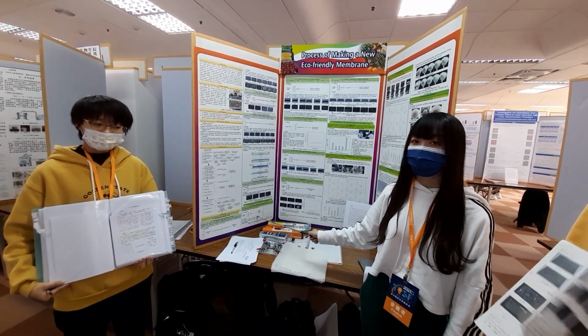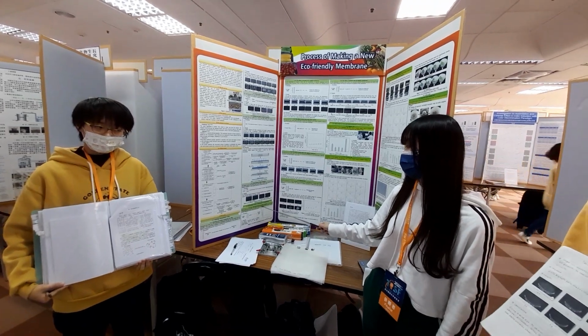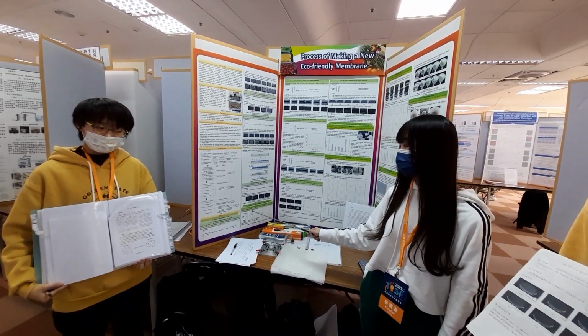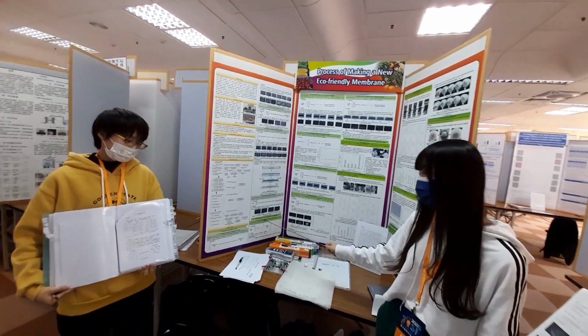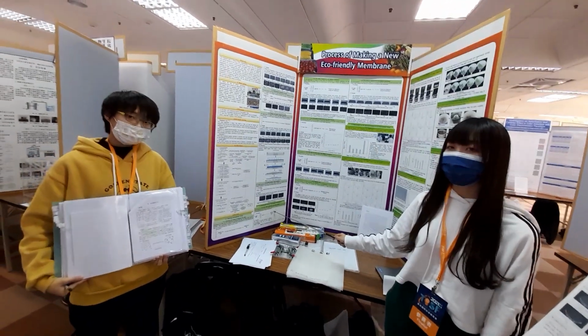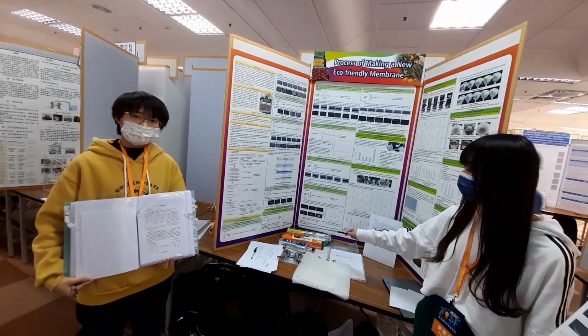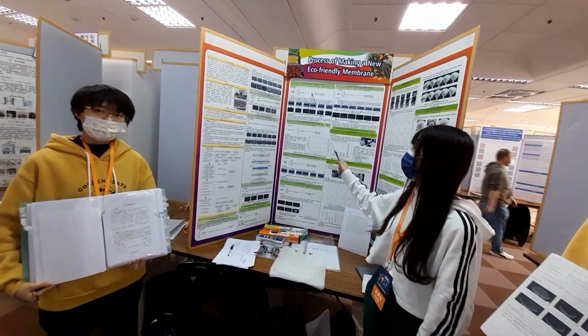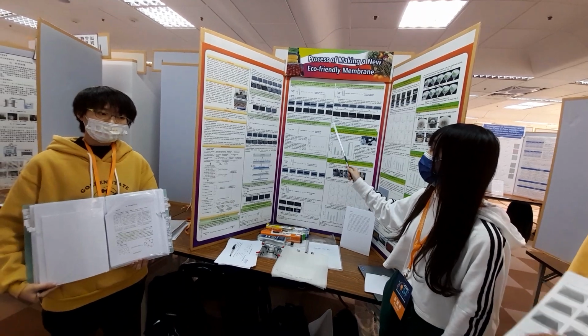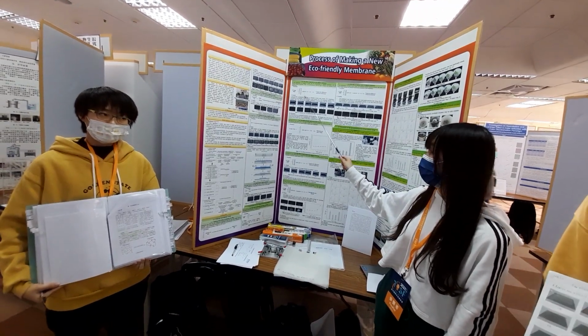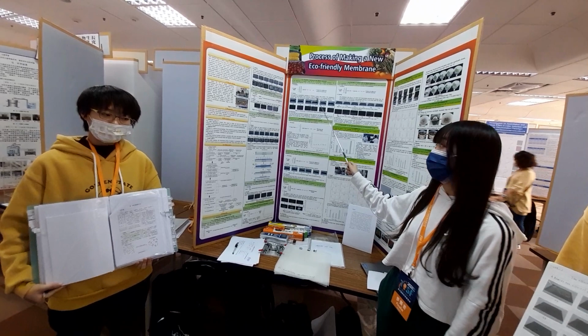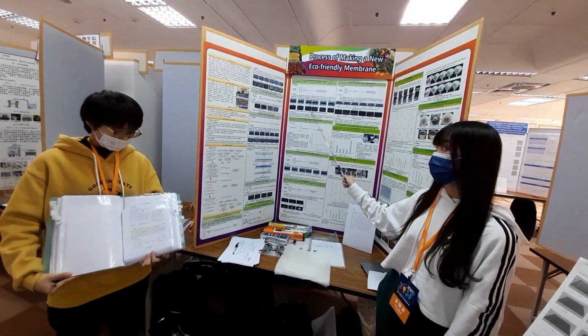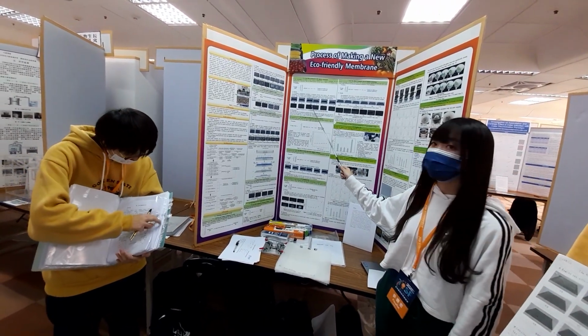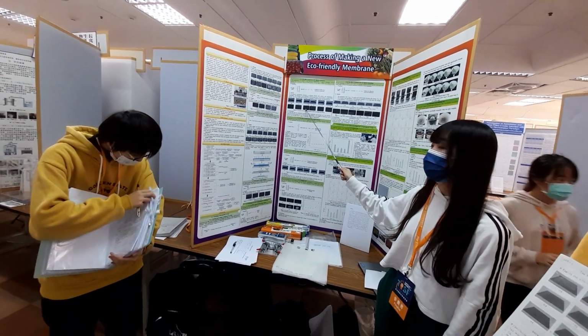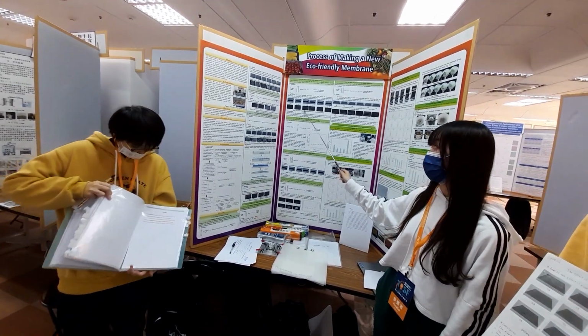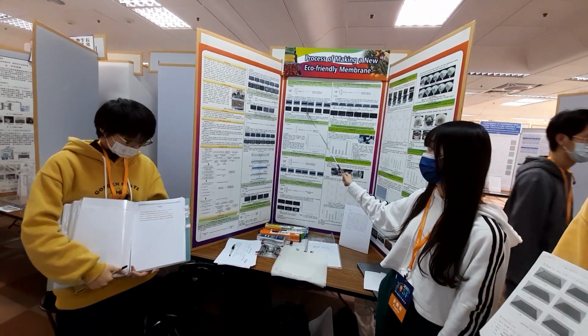So how did glycerin and acetic acid impact the membrane property? First, we want to discuss the effect of glycerin on the paste viscosity. We can see that it didn't show an obvious trend. After we make it into a membrane, as the glycerin concentration increased, the membrane became more uneven. So we choose the one with 2 grams of glycerin to be the best one because it is the most even one and it has better transparency and adhesion to the plastic.